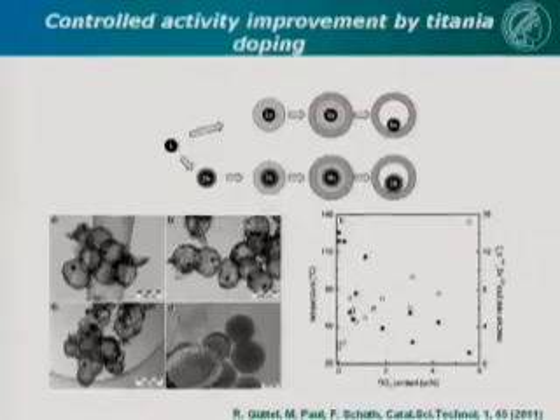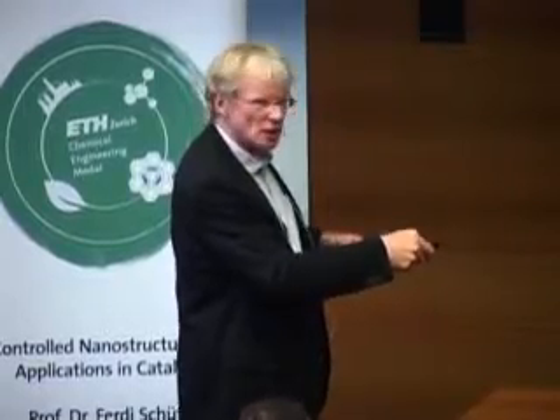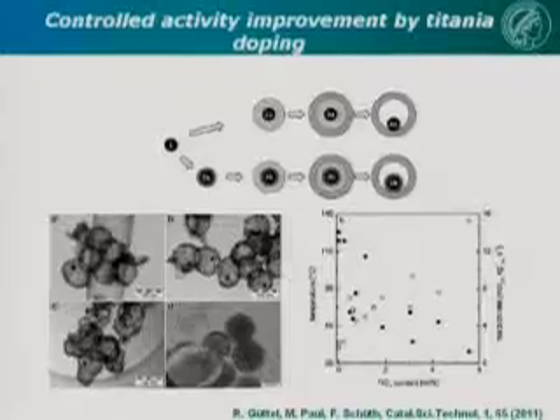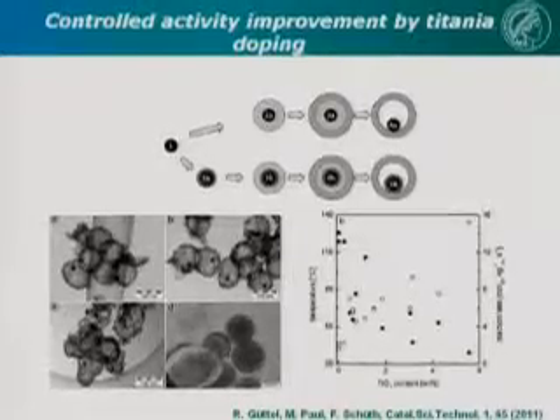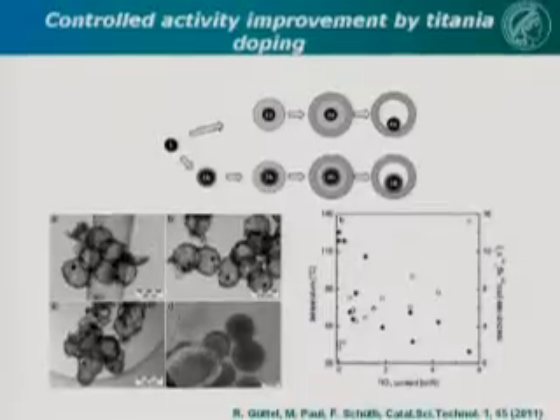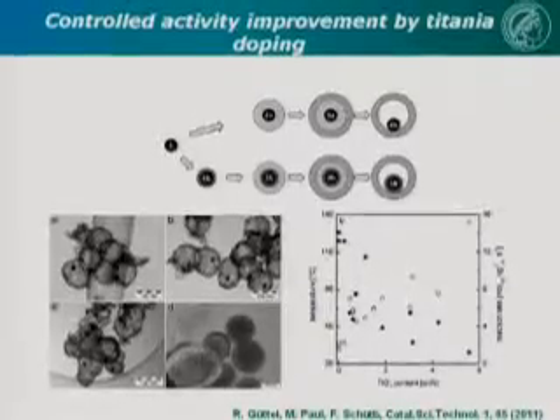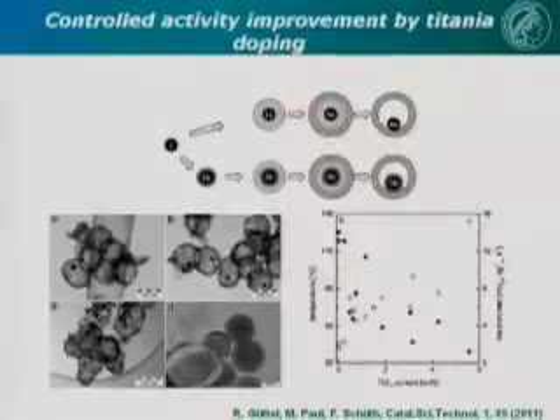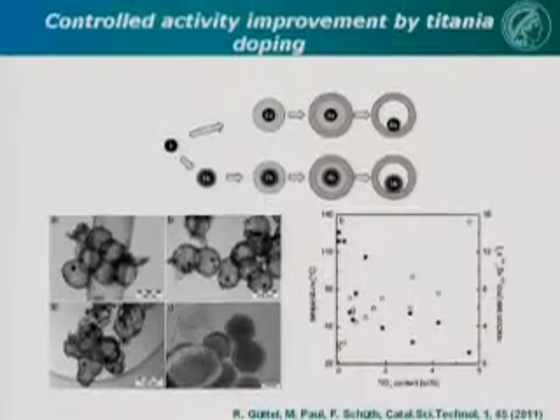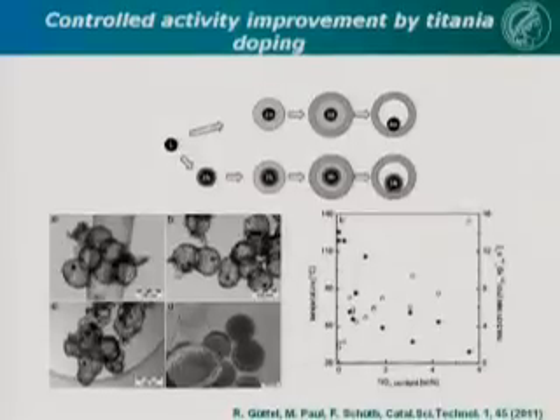It's the temperature for 50% conversion over the titania content decorated onto the gold particles. And there is a very clear trend. If you increase the titania doping, your activity goes higher because the 50% conversion temperature decreases. So titania in this model catalyst really has a beneficial influence on catalytic activity.